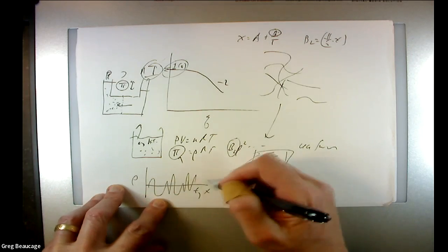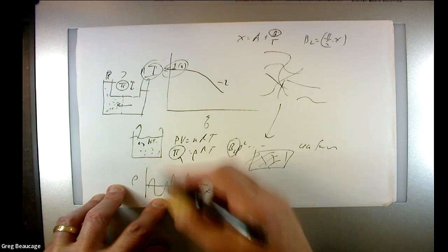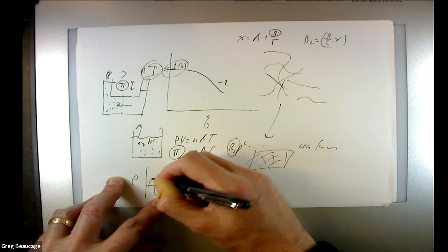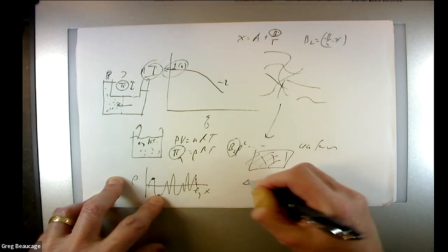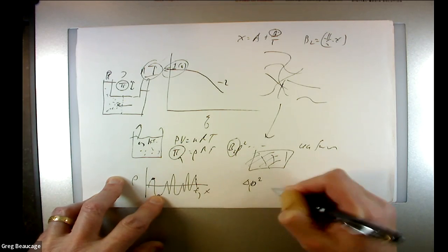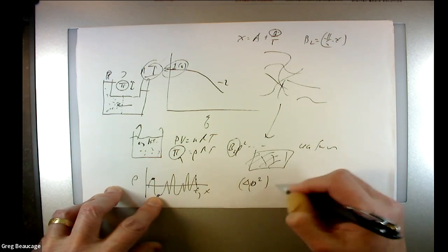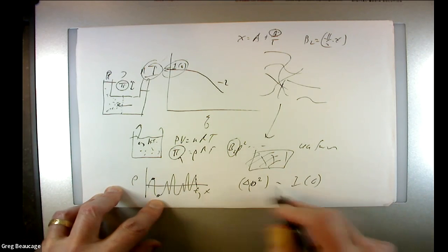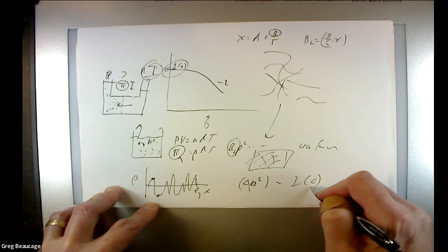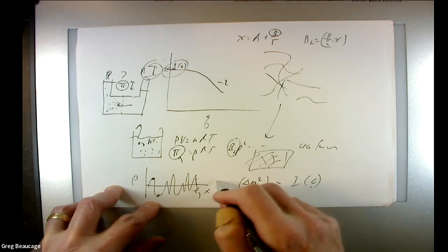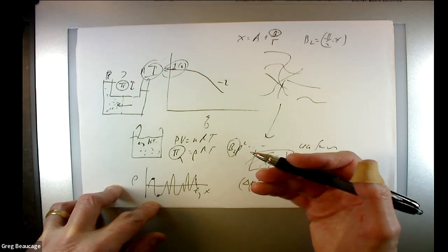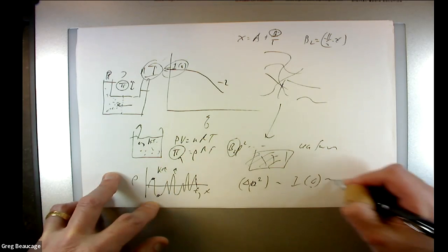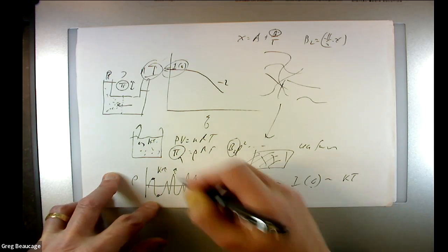Anyway, so we have these fluctuations, and that's what gives us the contrast. These two things give you delta rho squared, the density difference squared. That's proportional to the intensity, I naught. So those fluctuations are what causes the I naught. If there were no fluctuations, you'd get no scattering intensity. And say kT goes up, then those fluctuations go up. Something's going to be proportional to kT.